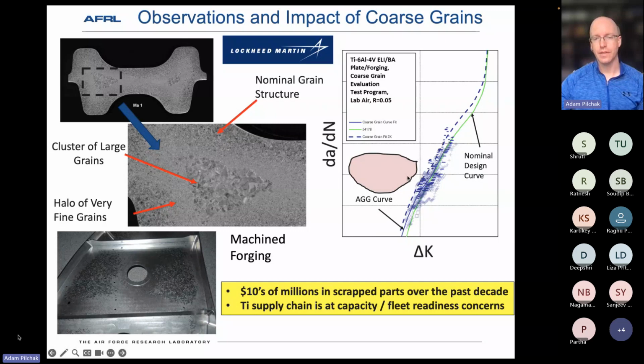They also grow at faster rates than their long crack counterparts for stress intensity ranges that are greater than delta K threshold. And this kind of accelerated rapid growth can persist up to many microstructural dimensions. The kind of rule of thumb is somewhere between 5 and 10. And so now if we have grains that are of the order of several millimeters, and I extend that out to 5 or 10 microstructural dimensions, we can have multi-millimeter sized cracks develop before they follow the classical design curves quite well.